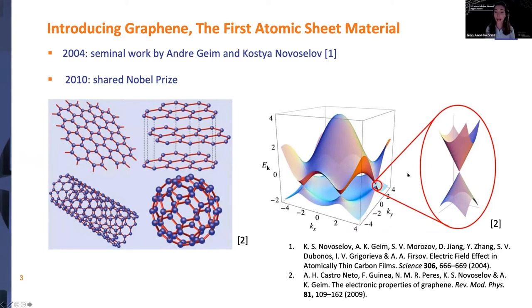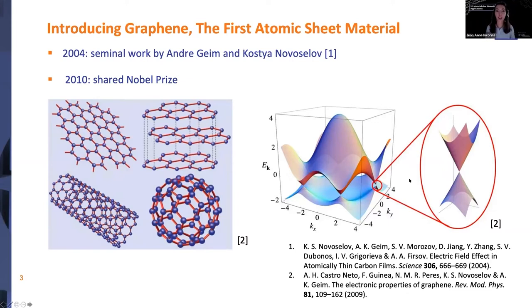The first famous property graphene showed is that you have massless electrons that can exist at certain momentum points in space. This is illustrated by the energy versus momentum plot, where we can see the points at which the valence band and conduction band meet, and where electrons can behave somewhat like photons. Just the fact that by confining a material to two dimensions these very new emergent properties arise is really where the strength of 2D materials lies.